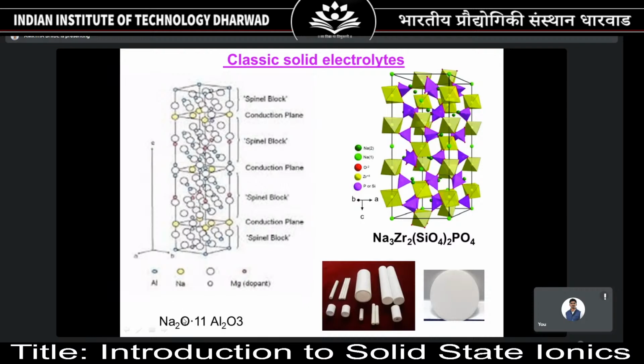Basically, it's a sodium oxide with alumina. So you get a structure. You can look at this structure over here. You have a spinel block, and there is a small arrangement of atoms in a vertical section. It has reduced. Again, you have a spinel block, and again a narrow block. It's like a bottleneck structure, and these yellow colored larger spheres, which I am showing here, are enabled to travel in this open structure.